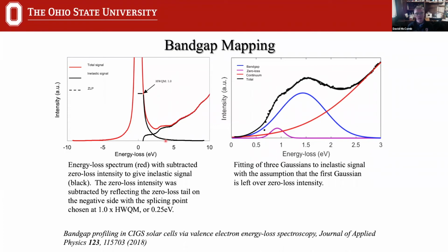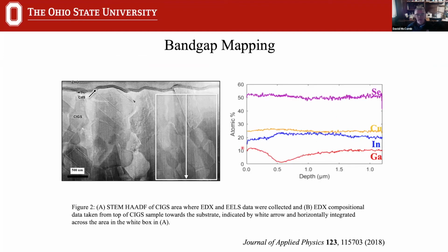So one thing that we decided to do with Julia was, well, let's be conservative. Let's deliberately underestimate the amount of zero loss peak that we're going to remove, which means that we know that we won't get anything unphysical, but we do know that when we subtract that zero loss peak, we will get a signal in here that is actually still due to the zero loss peak. It's not due to the signal that we're looking at. So that was our assumption. And then we started to fit Gaussians to these. We said, well, let's assume that the first Gaussian is associated with the zero loss peak, so let's look at the properties of the second Gaussian.